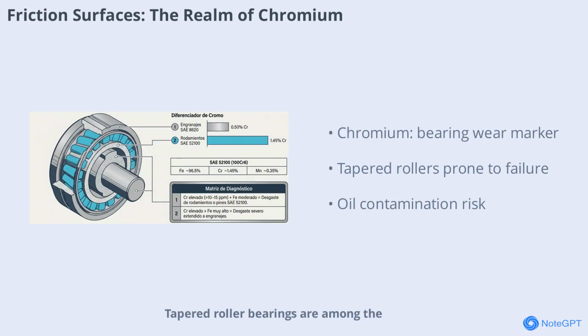Tapered roller bearings are among the most failure-prone components in the final drive, due to constant load and oil contamination risks. These bearings rely on chromium-rich surfaces for wear resistance. When oil analysis detects elevated chromium, it often signals bearing wear. Monitoring chromium levels helps anticipate bearing failures before they escalate, allowing for timely intervention and reduced downtime.